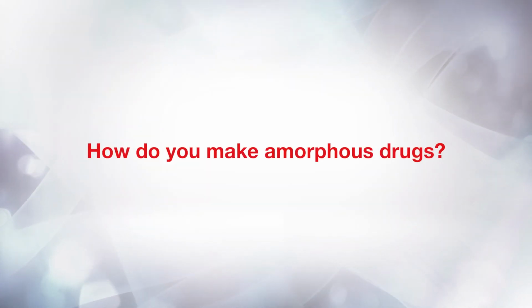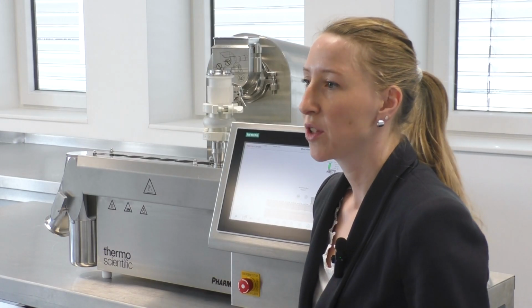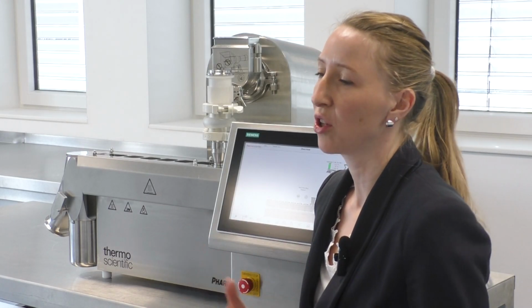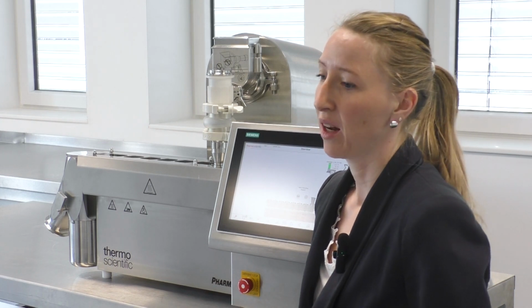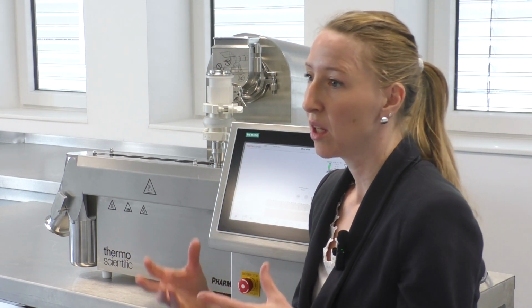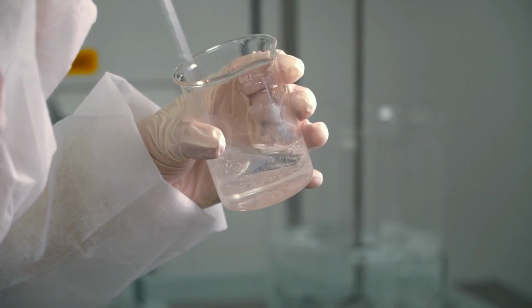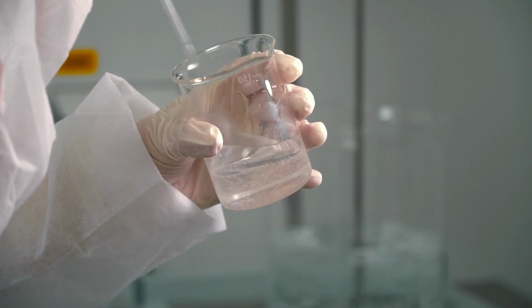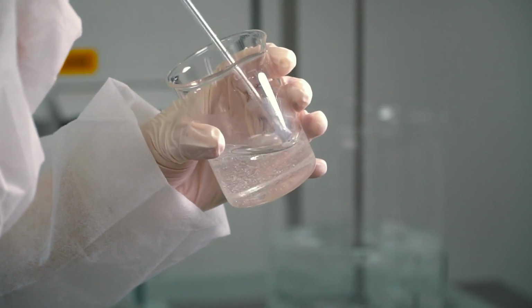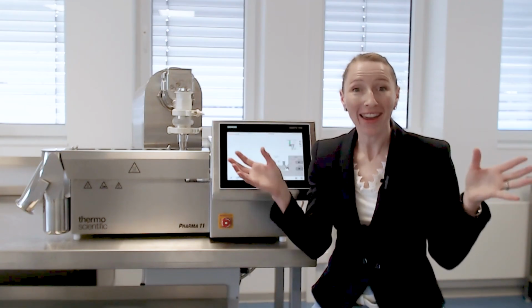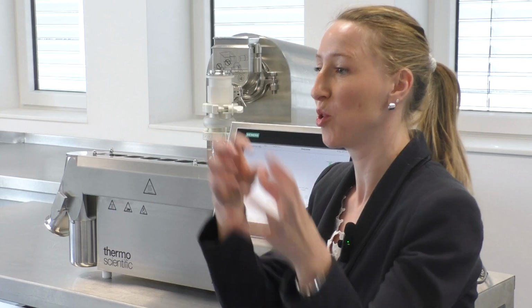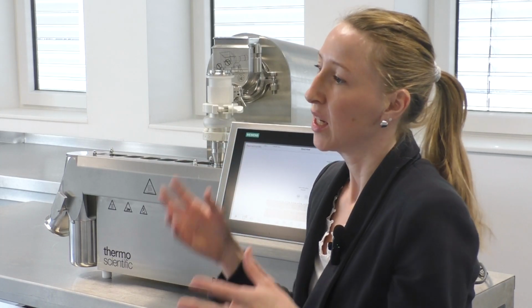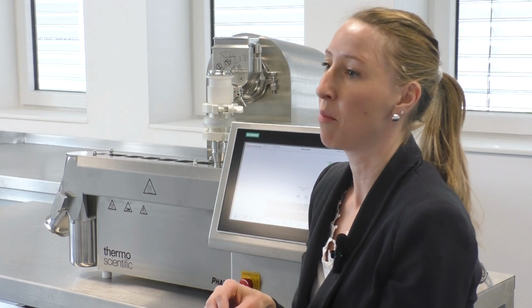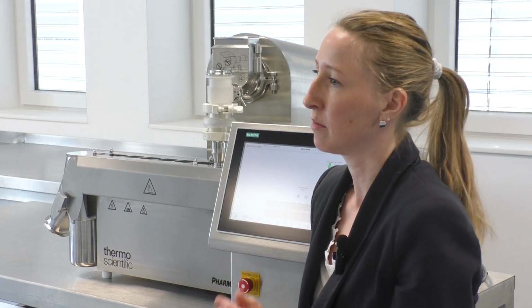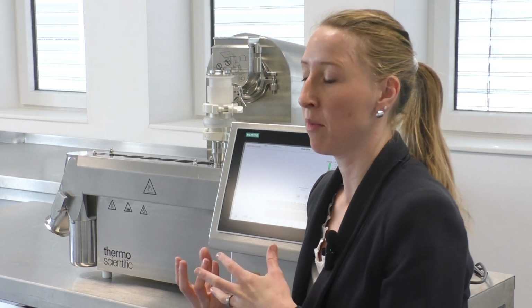There are different possibilities to reach an amorphous state. For example, you can use a traditional technology like spray drying, where you dissolve your formulation, so the excipient that's helping to keep the amorphous state, plus the active pharmaceutical ingredient, into a solvent, and then you spray dry it. So you produce, from that solution, a powder, and that one is then an amorphous matrix, and typically also an amorphous drug. And that's a very nice and good way to make a drug amorphous.